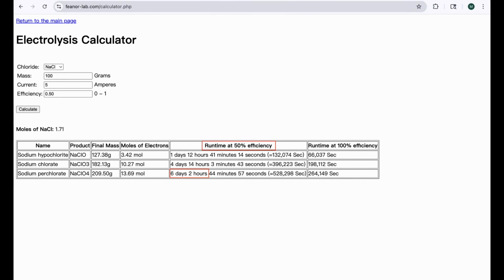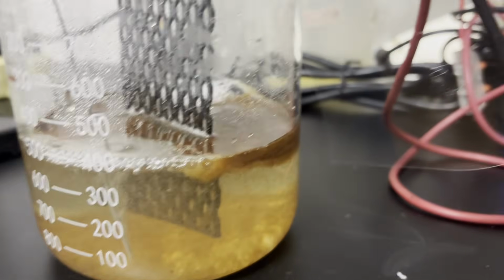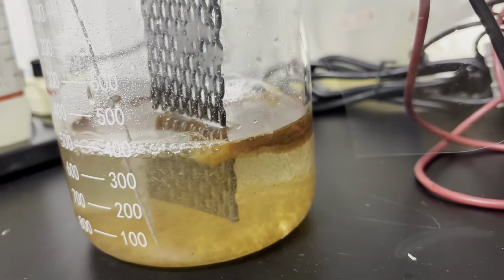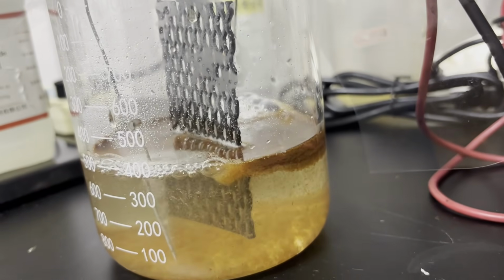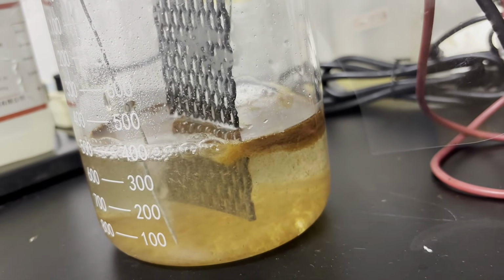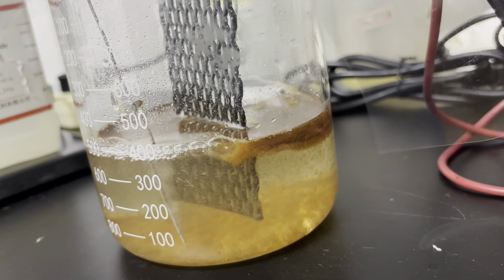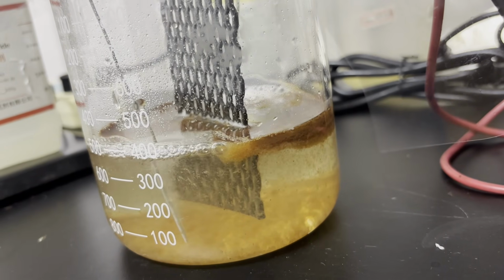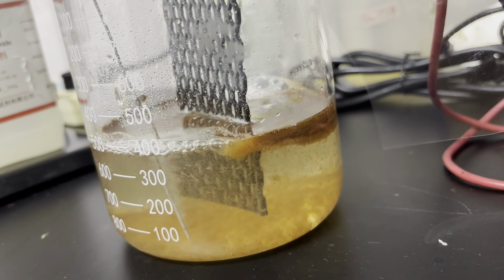At 5 amps, it would take me around 6 days and 2 hours to convert all chloride to perchlorate, but the real runtime of the cell was close to 9 days, which I'll explain why later. The electrolyte was brown due to lead dioxide particles, as I accidentally connected the negative to the lead dioxide electrode. Lead dioxide electrodes can only be used as the anode, never the cathode, or else the lead dioxide layer will flake off due to reduction.